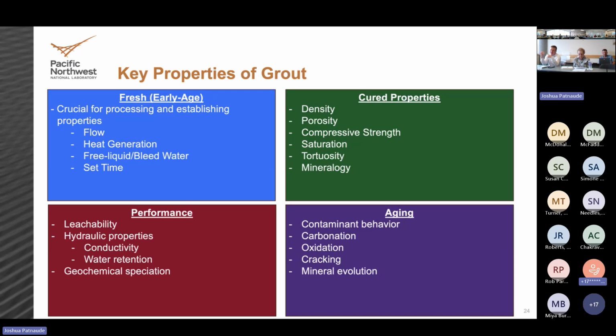TCLP is designed to screen materials that go into landfills. It's a very bulk, extreme environment test. You take your material, crush it up, put it in a strong acid, see how much stuff is released, and determine whether you stay above or below a threshold.